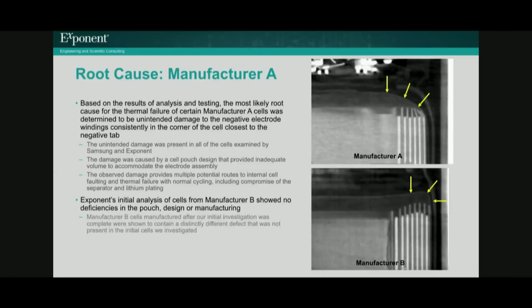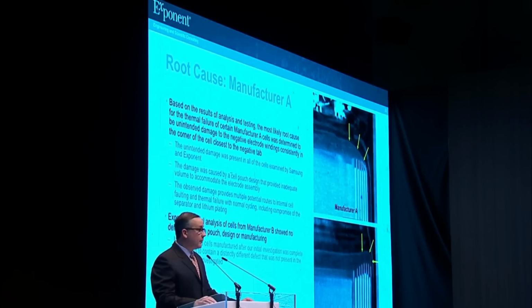Negative electrode damage like this is undesirable because it can put strain on the separator, causing separator failure and cell faulting. Or it can cause negative active material delamination that can upset the local capacity balance, resulting in plating and potential cell faulting. Cell faulting is a well-known route to the types of thermal failure that were seen in these cells. This evidence was sufficient for Samsung to trigger a recall of the devices equipped with cells from manufacturer A.